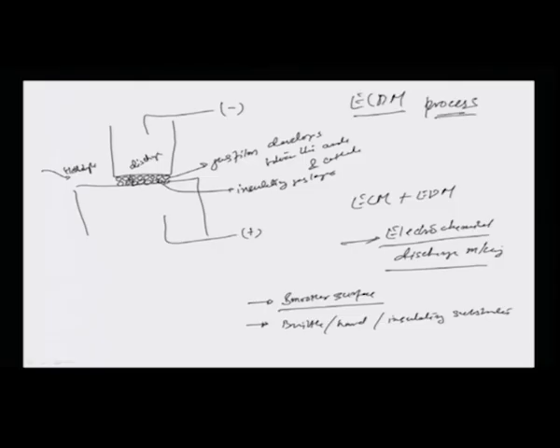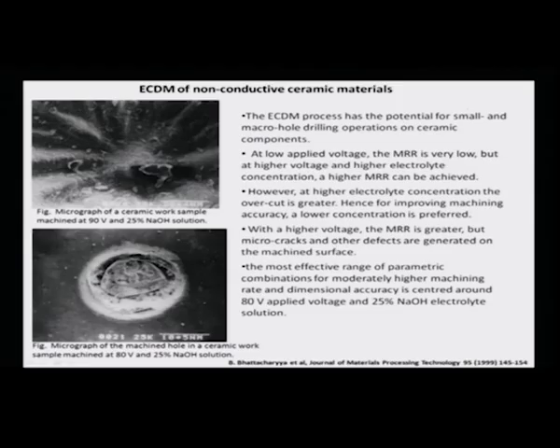So this is the beauty of this ECDM process, and I am going to just give a few examples where ECM and EDM are combined together for machining certain non-conducting ceramic materials. For example, in this particular case you can see there is an ECDM process which has been able to carve out a small complex feature in a ceramic work sample, and this typically is machined at 90 volts with a solution of sodium hydroxide 25%, and although the MRR is very low at high voltage and high electrolyte concentration, MRR is something which can be improved probably by varying the concentration and voltage values.